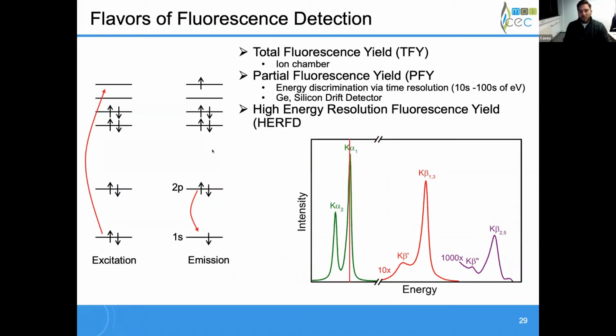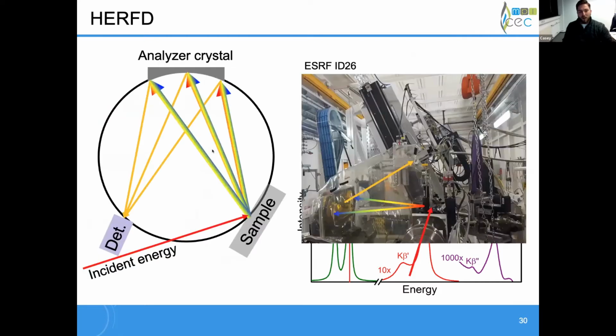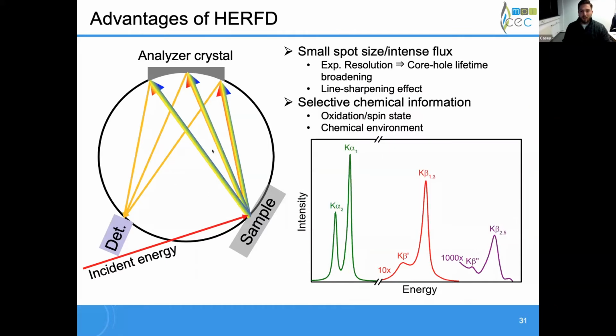And last and most precise is HERFD, or high energy resolution fluorescence detected spectroscopy. Here we use an actual emission spectrometer, which involves a detector, a sample, and an analyzer crystal on a Rowland circle to selectively choose only photons of a given energy. Therefore we can detect, for that given energy, how it varies as a function of incident radiation. Out of that, we can get our HERFD absorption spectrum. Since we're using an emission spectrometer, we tend to need a lot more flux because we're throwing away a lot of photons; we have a lower effective solid angle. But with a really small spot size and intense flux, we can get an experimental resolution that approaches the core hole lifetime broadening of the system that you're looking at.